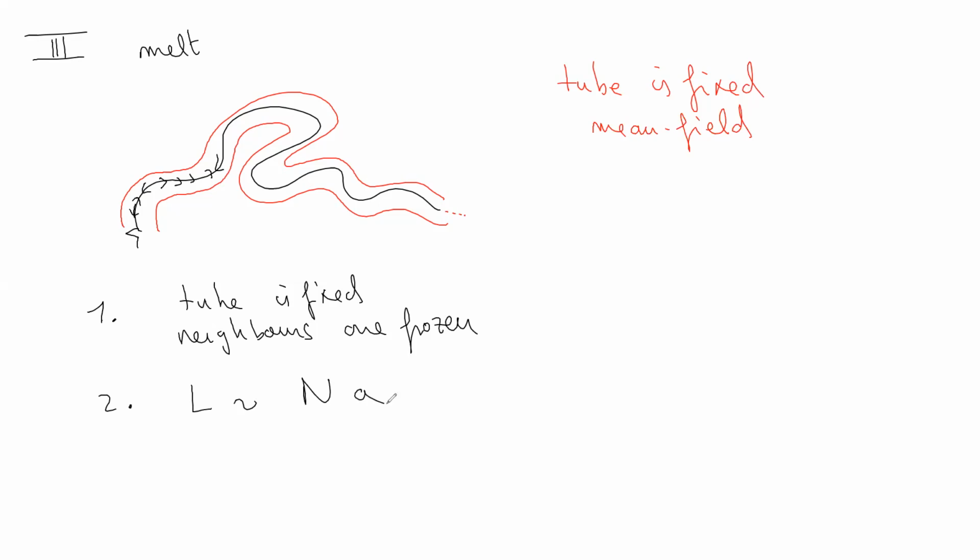It's a polymer chain with n monomers, each having a length A. Now, inside this picture, we are dealing with a Rouse-like problem because we have monomers everywhere around, and we are really in a melt. So if we are in a melt, the Rouse dynamics works, and so the diffusion coefficient is basically something which is 1 over the number of objects. Every monomer is frictional, is damped by the neighbors, okay, in the Rouse description.